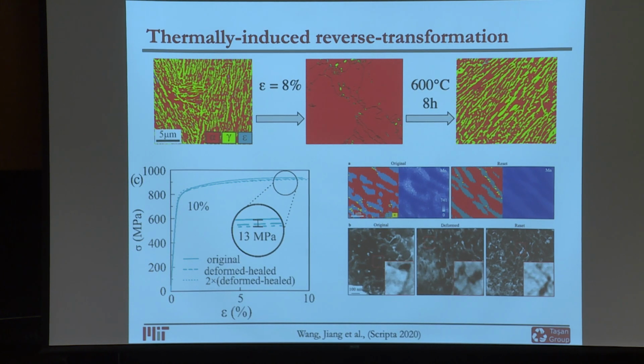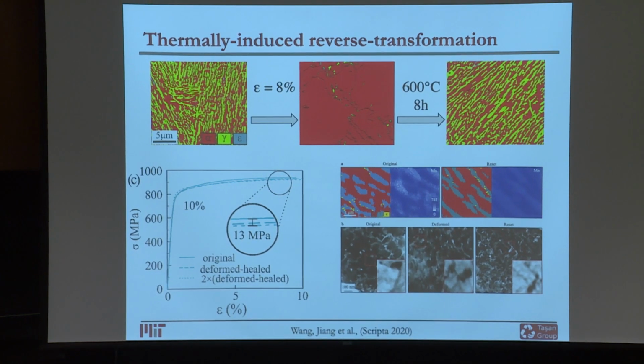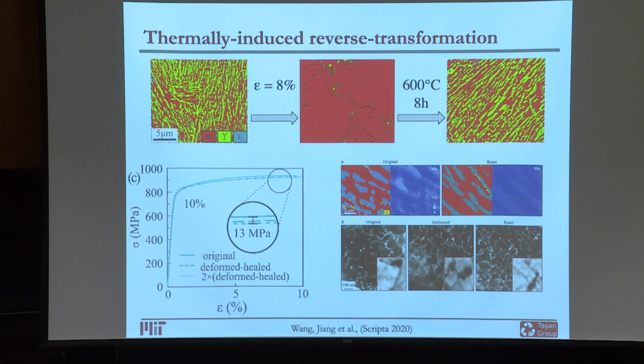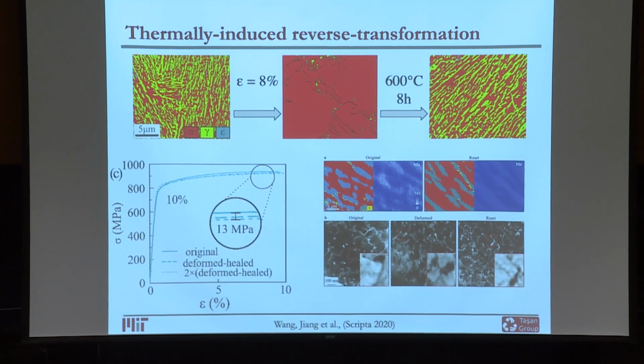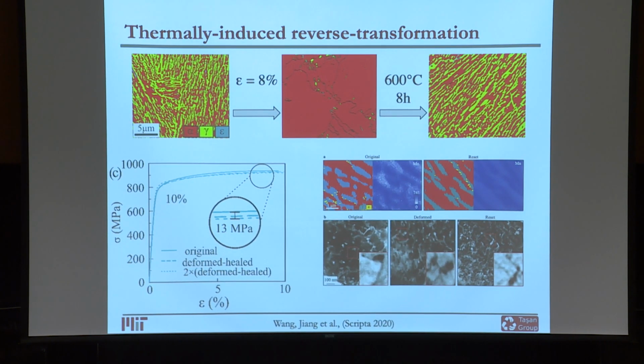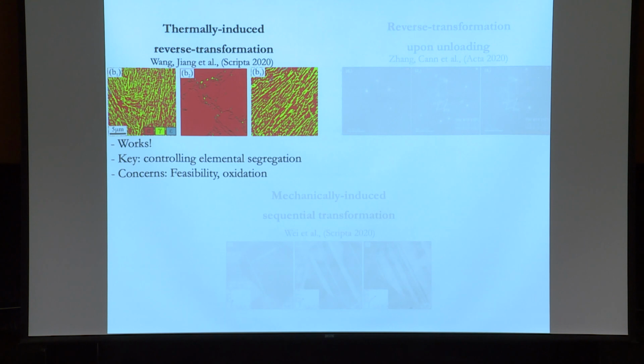So why does this work? This works because the transformation that is taking place forward and backward here is really controlled by local segregation of alloying elements. In this case, we are using manganese segregation cleverly to be able to control where martensitic transformation is going to take place, and then reverse austenitic transformation is going to take place. So the key here is the design of this microstructure that's going to give this chemical heterogeneity that gives us the benefits. So that's the first approach. We are doing a heat treatment to get the microstructure back to its original state.